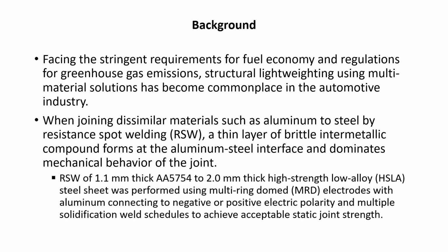Multi-material solutions have become commonplace in the automotive industry. But when joining dissimilar materials, such as aluminum to steel by resistance spot welding, a thin layer of brittle intermetallic compound forms at the interface and dominates the mechanical behavior of the joint.